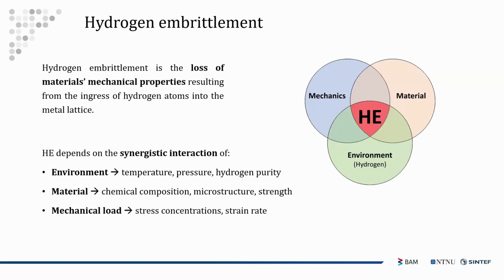So as it was told before, hydrogen embrittlement is an environmental degradation that consists in a loss of mechanical properties, and particularly tensile properties, that result from the ingress of hydrogen atoms within the metal lattice. So basically this physical phenomenon relies on the synergistic interaction of many factors. Although it has been widely studied in the past, it has not been fully understood so far. It relies on the effect of the environment that should contain hydrogen, of course, and more particularly on the temperature of the operating environment, but also the pressure and the hydrogen purity.